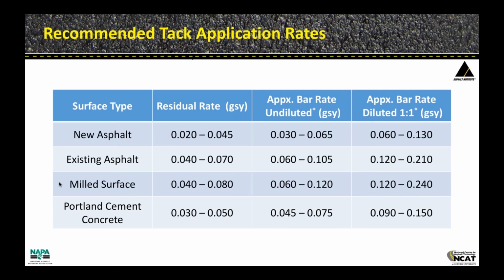The next column over is the approximate bar rate. So if you have an undiluted emulsion, you're going to obviously spray a little bit higher rate, because that has some water in it. And then to the far right, if you diluted that 1-to-1. If you're on an existing asphalt surface, obviously that's going to be a little more hungry for asphalt, a little more porous, quite likely. So you're going to typically see higher application rates. The same is true for a milled surface. You've got more surface area there. And then Portland cement, somewhere in between a new asphalt and an existing or milled surface. So again, very important that we get enough material down, get the right residual rate, and make sure that it's put down uniformly, both transversely and longitudinally, and that it stays there.